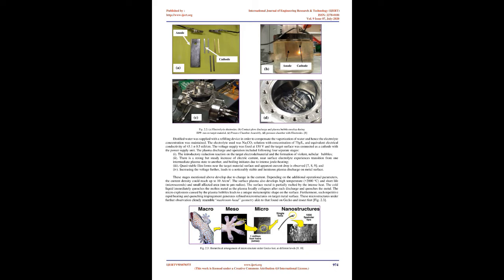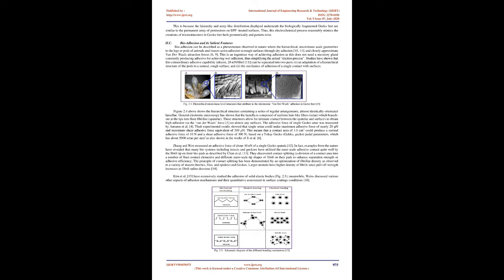The mirror-polished samples were then subjected to EP treatment at 150 V for 5 minutes and 15 minutes, respectively. The EP cell has similar components of electrochemical cell as shown in Fig 2.1. The CGD, contact glow discharge, configuration was adopted, hence, the electrical circuit remains the same except that the bath solution was enclosed in a chamber, which could be sealed and pressurized, Fig 2.2, C. Argon was used to pressurize the chamber, since pressurized argon could dilute the hydrogen and oxygen generated from electrochemical reactions for safety purposes. Figures 2.2, A, and D, represent the electrodes and assembly of the electrodes, respectively.